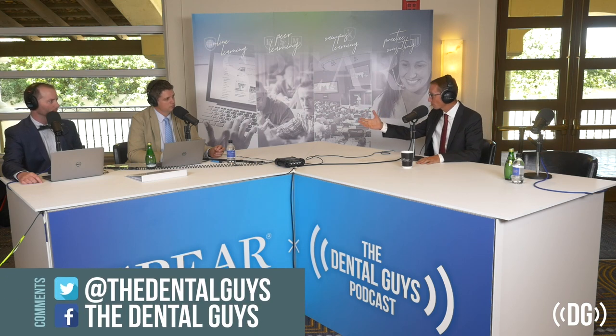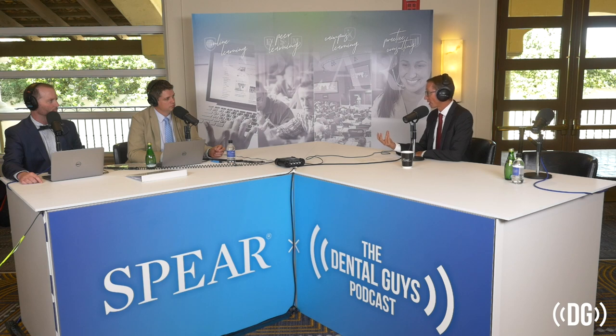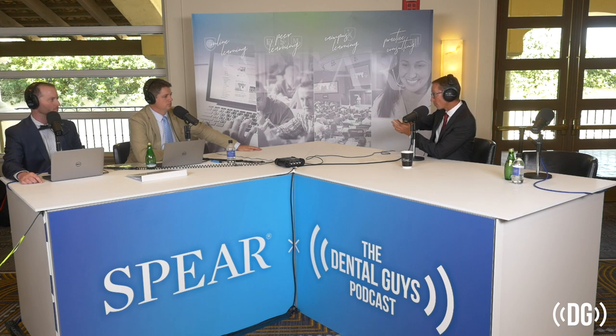Conventional cements and composites don't work. You need to have certain monomers in it, and that's what he looked at. What they did, though, they bonded to a flat surface. Typically, in our research, we polish the surfaces so they're all uniform. But when I looked at some of the crowns inside, that's not a flat surface. And this one we actually moved over to using the primer, because we understood that this highly filled composite wasn't able by itself to bond successfully to a roughened surface. To flat, yes, but not too rough. And that's when we came with the primer.